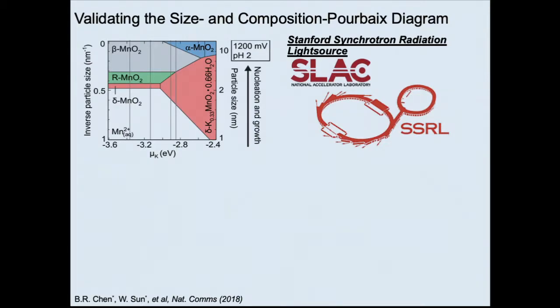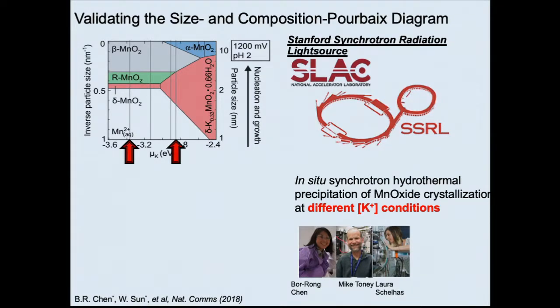And then we can see, can we predict what goes on in the experiment? So we work with SLAC, and they did experiments in this phase diagram at a few different chemical potentials of potassium. When you're very negative, that's essentially almost like no potassium. So what we would predict is that you would start with Mn2 plus in solution, form birnessite, which is the delta phase, then go to ramsdellite, and ultimately form the equilibrium beta MnO2.